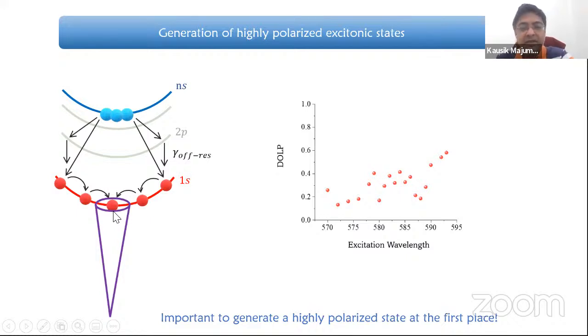And this usually happens through phonons, so you lose the coherence or the polarization information. Here is one experimental data that we have on WS2. Here we are just coming down in the excitation closer to the 1s state, and you see your observed DOLP, or the valley coherence, is actually improving because you're losing less information, or less randomization of the information, due to this kind of phonon scattering.